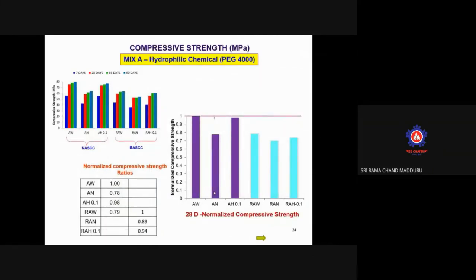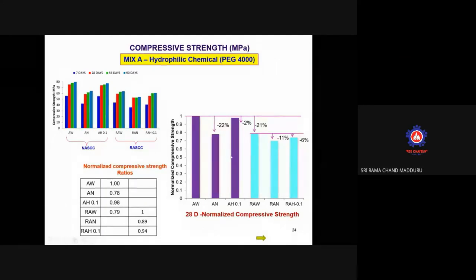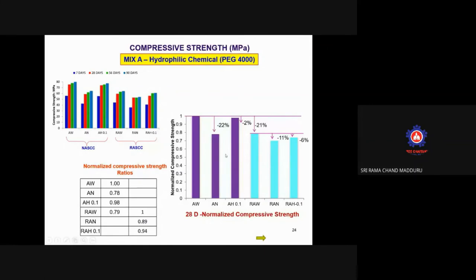if normal concrete is achieving 100% strength with water curing, when no curing is there, there is a reduction of the strength by 22%. But there is only 2% reduction with the help of self-curing chemicals. That means you need not do curing for 28 days or 14 days, the specified age of curing. You just simply add these self-curing chemicals in concrete during the mixing time and they will take care of it. Somebody may ask me, what is the increase in the cost? And you can see polyethylene glycol is being used in food products. The cost is very much cheaper, around half kg costs around 50 rupees, something like that,